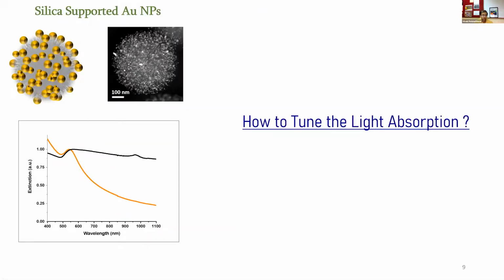Now, coming back to the question that I was trying to ask: how do I design a material which absorbs the entire sunlight and at the same time is also catalytically active? So we wanted to use the surface plasmon resonance properties of gold. But if I simply take the gold nanoparticle and load it onto the silica, something like this, the light absorption is like this orange curve, where around 560 nanometer is the lambda max, and some weak absorption in other parts of the visible and near IR.